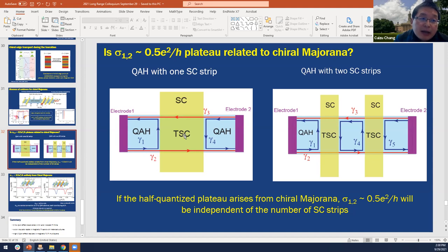But as David said, I don't know if we could systematically introduce some barriers between the quantum anomalous Hall and the superconductor layers, and if we could get the proximity effect, but at the same time the superconductor layers cannot short the two chiral edge states. It may be possible we could use this configuration to detect the Majorana physics, but it should definitely be at the nanometer size level rather than the millimeter size level. That's my comment.